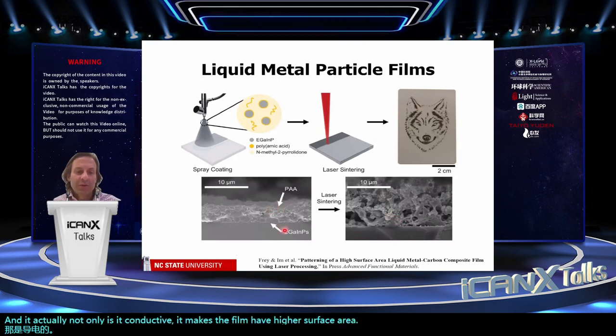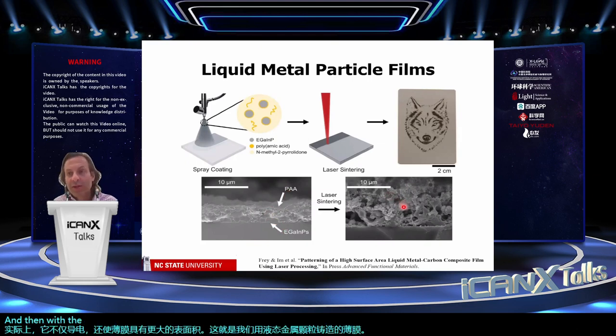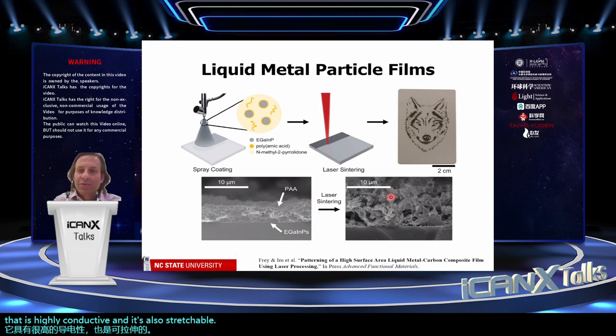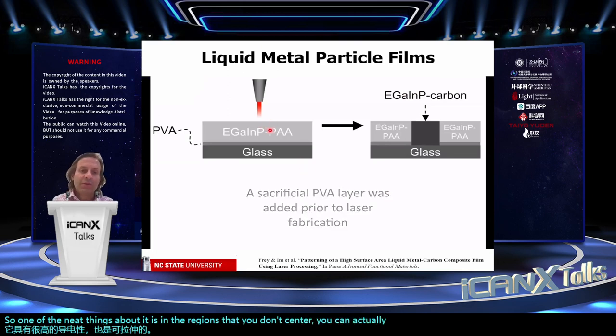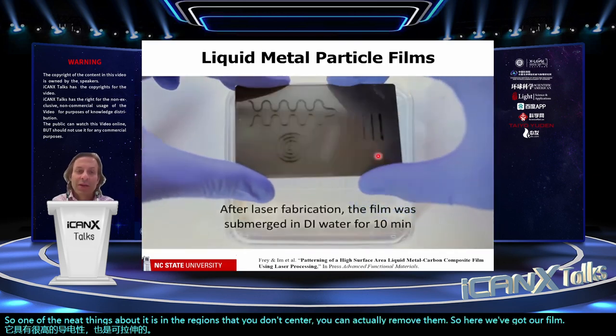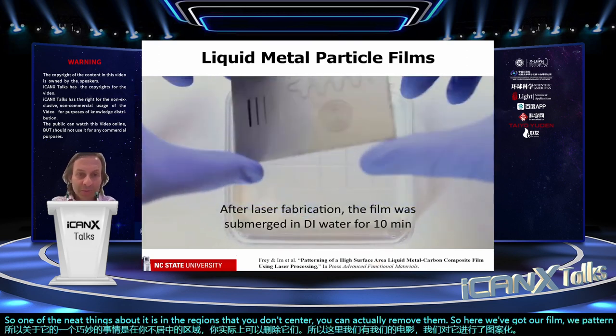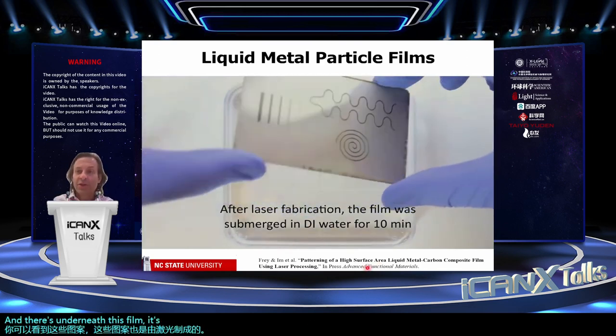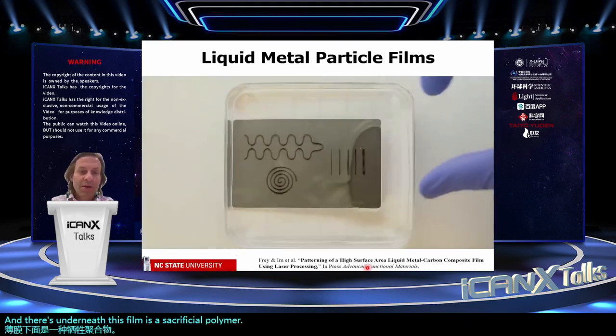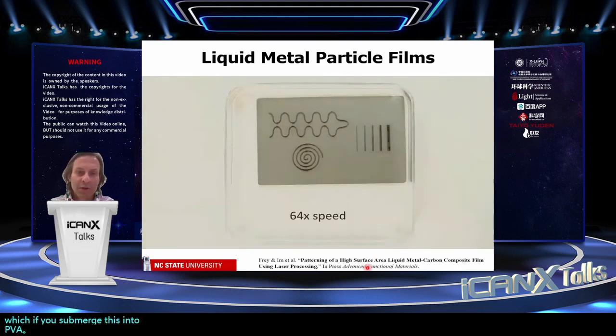So this is the film as we cast it with the liquid metal particles and a little bit of the polymer, and then with the laser, it actually expands and forms carbon. So we make a composite film of liquid metal and carbon that is highly conductive, and it's also stretchable. One of the neat things about it is that the regions that you don't sinter, you can actually remove. So here we've got our film, and we pattern it. You can see the patterns, which again are made by the laser. Underneath this film is a sacrificial polymer, PVA, and if you submerge this into water, the water will go under the film and release it.